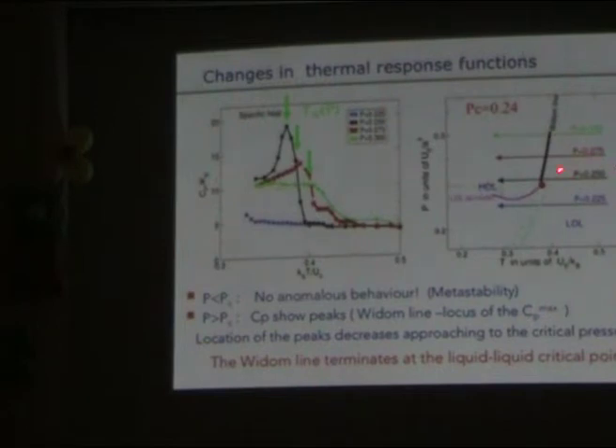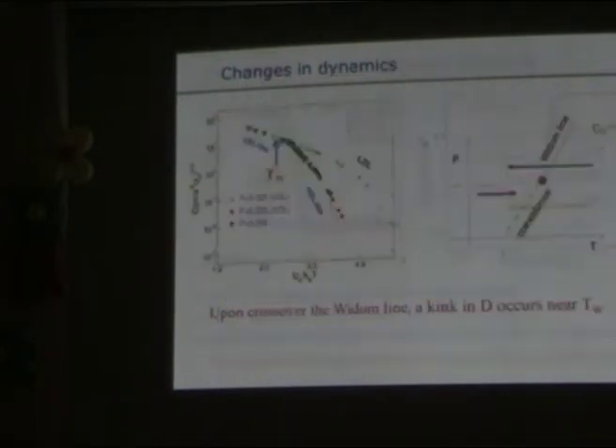So this means that in the one phase region, according to what we learned from statistical physics, we are not supposed to see anything, but we now found some response function maximum, and it really can be measured by experiment. Actually, it's not only for this specific heat. There are many other thermodynamic quantities, such as the isothermal compressibility, that also show similar behavior.